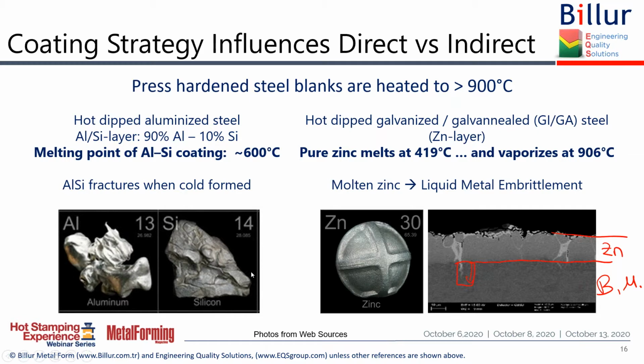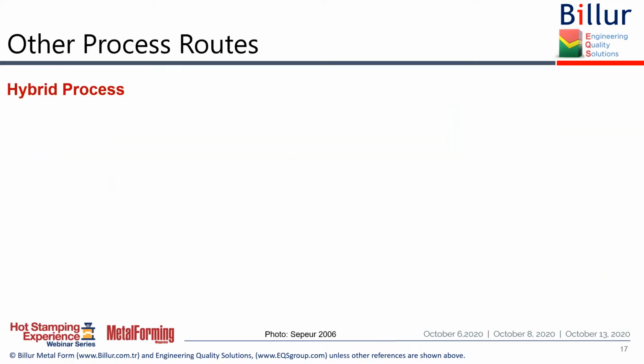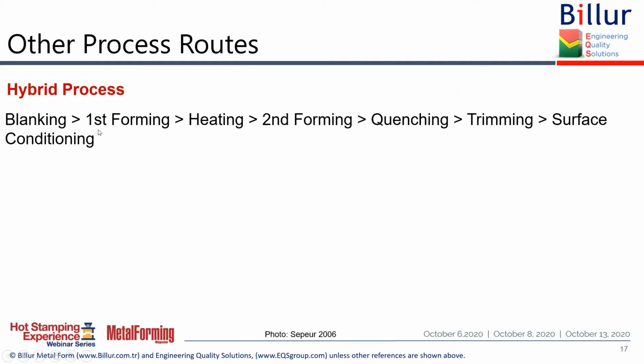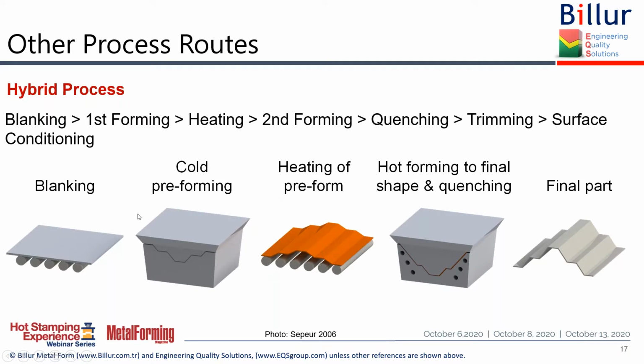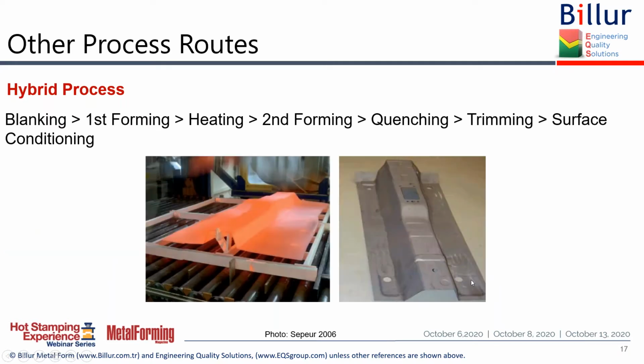Now, I said 10 different process routes. Let me go very quickly over the other ones. There's one I call as hybrid process. Here we make blanking, make a first forming, heat the already formed preform, make a secondary forming, quench, trim, and surface condition. This was the first method to make deep parts, such as the transmission tunnel.